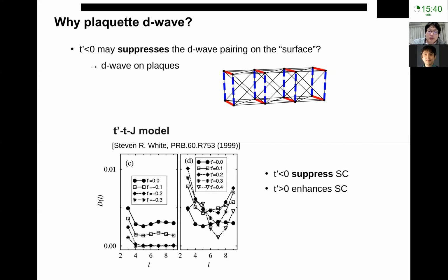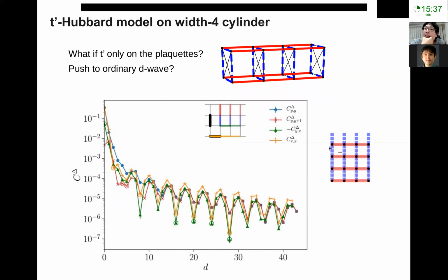To further test this idea, we consider a system where we have T-prime, the cross hopping, only on the plaquette but not on the surface, to see whether this would push the superconductivity back to the surface. We actually found this is the case: if we consider this kind of system, then the pairing symmetry goes back to the ordinary D-wave, where the correlation between the vertical and horizontal bonds have opposite sign, and the horizontal correlation is comparable to the vertical correlation.